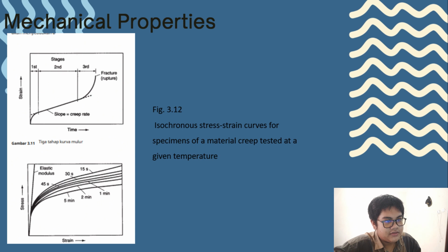We get to figures 3.12 and 3.11: the three stages of the creep curve and the isochronous stress-strain curve for a specimen of a material creep tested at a given temperature. Here I have the creep deformation. Creep deformation refers to time-dependent plastic deformation that occurs when a material is subjected to constant nominal stress. The rate of creep deformation depends not only on the magnitude of the applied stress, but also on time and temperature. Continuing creep deformation over time ultimately leads to creep rupture, also known as stress rupture.